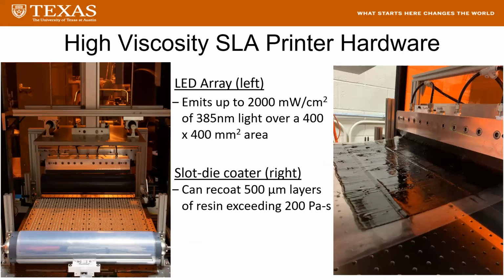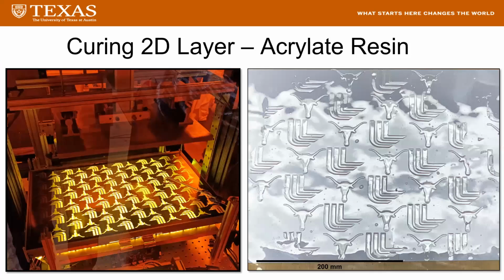You can see our 385 nanometer LED array at left emits a light field of 2000 milliwatts per centimeter squared over an area of 400 by 400 millimeters. And at right, our slot die coater there is recoating a resin. It can recoat viscosities exceeding 200 Pascal seconds or 200,000 centipoise in about 500 micron layers. And this was our first full-scale 2D patterning of a resin. This is another acrylate radical-based resin, and the pattern is about a foot per dimension with features as small as a few millimeters.